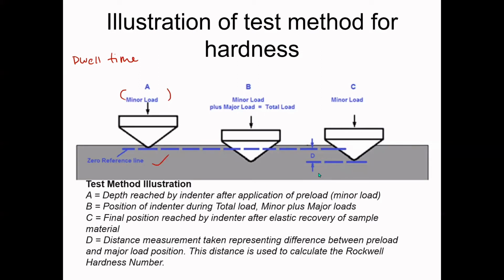And after the preload, an additional loading called the major load is added to reach the total required test loading. This force is held for a predetermined amount of time or dwell time, like what I have mentioned before, to allow for elastic recovery. And this major load is then released, returning to the preliminary loading. And after holding the preliminary test force for a specified dwell time, the final depth of indentation is measured, and the Rockwell hardness value is derived from the difference between the baseline and the final depth measurement.